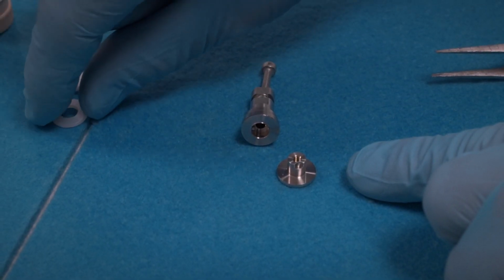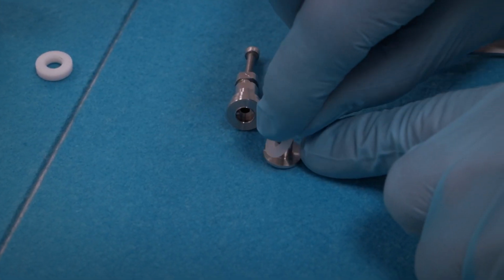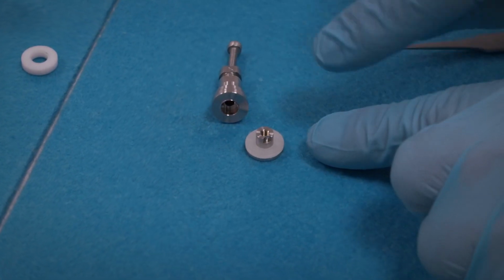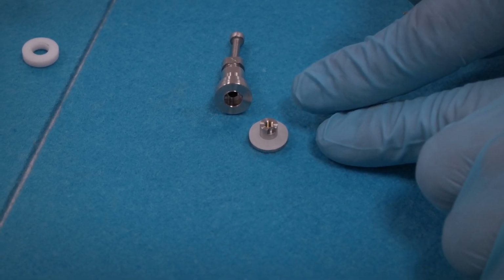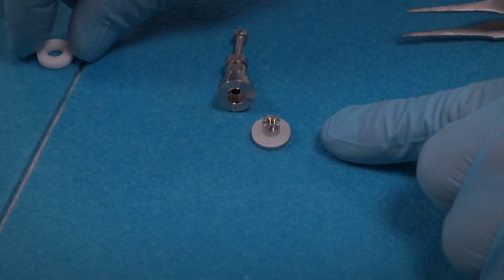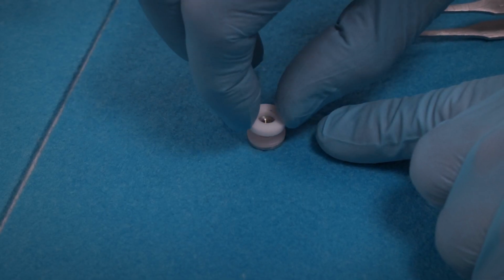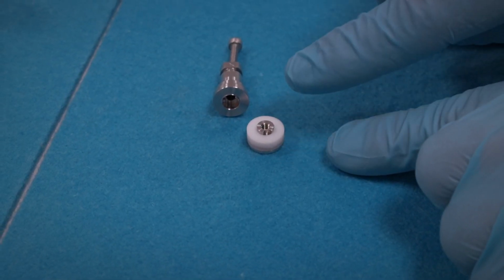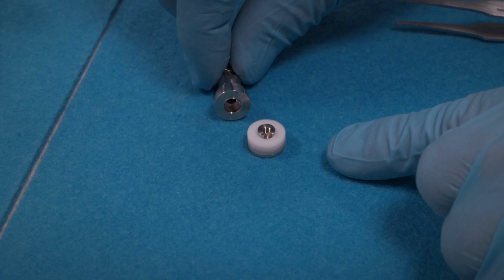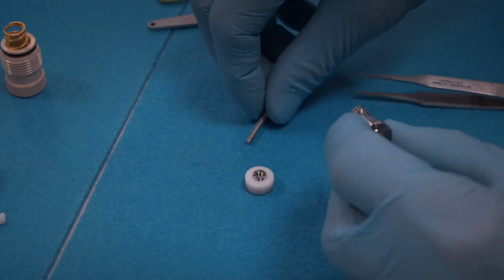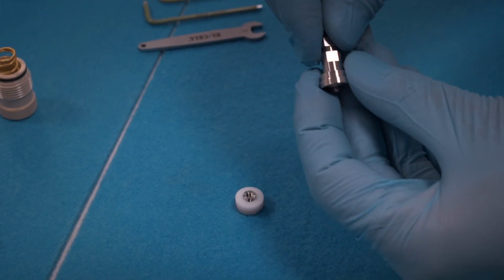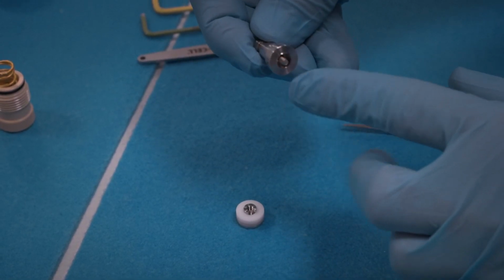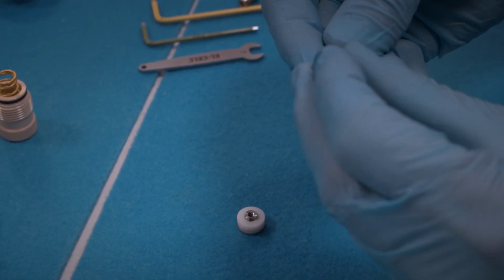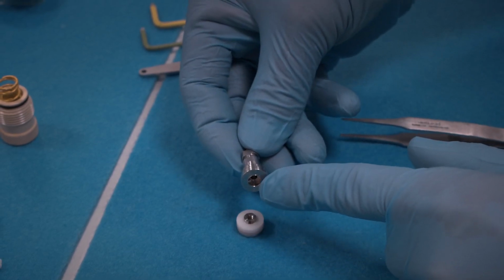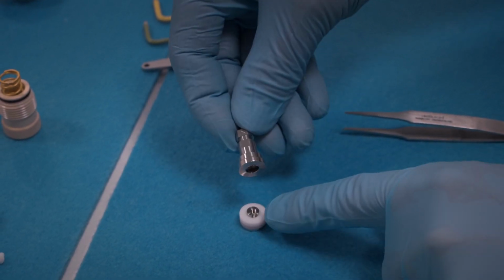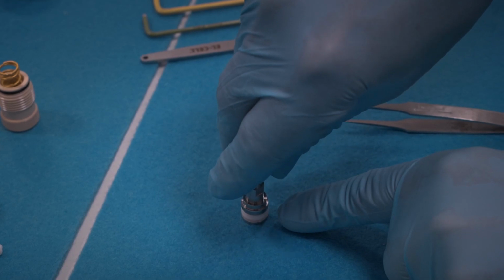The two sealing rings are curved and they have to be placed in such a way that the curvature is pointing up. First the polyethylene seal, then the PTFE seal with the same orientation. And then attach the lower part of the piston with a set screw inserted. Again, make sure that the set screw is aligned with a notch in the upper part.